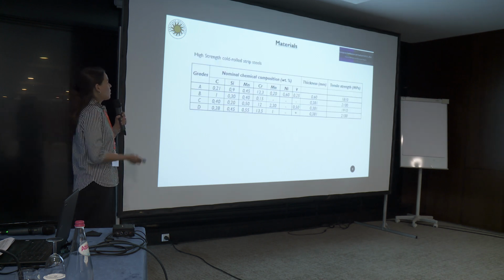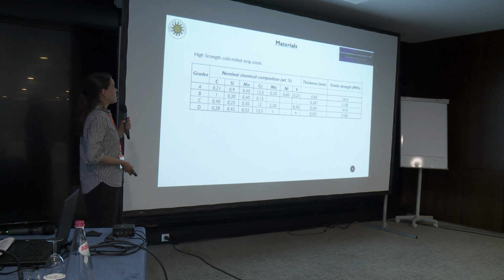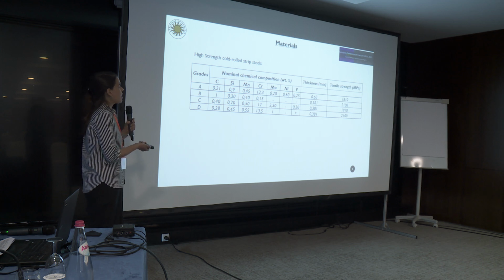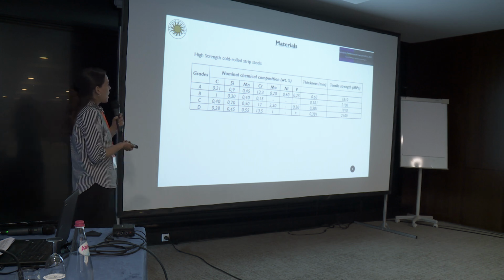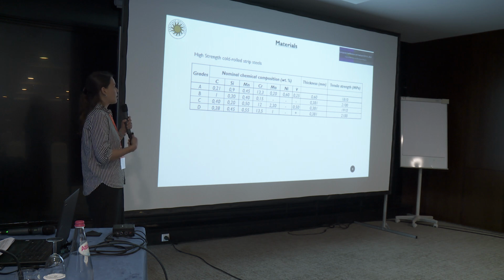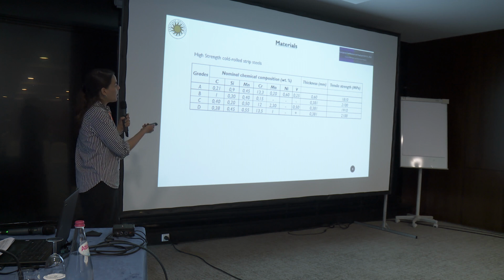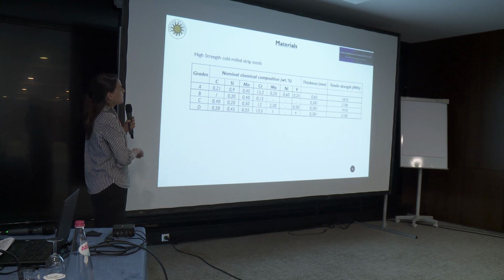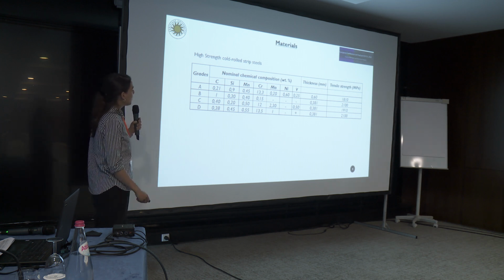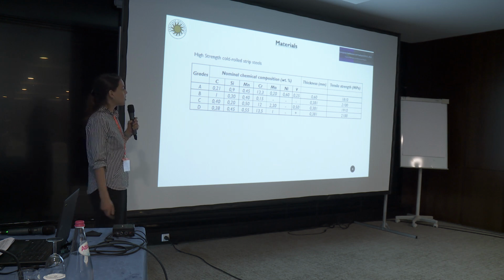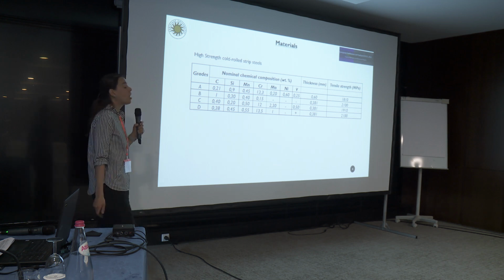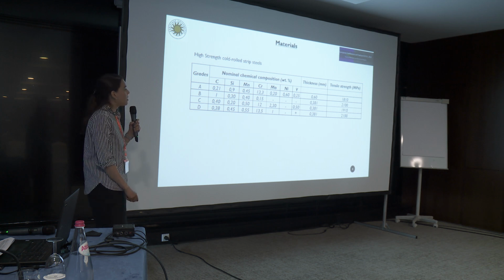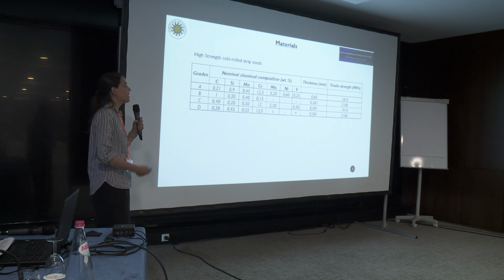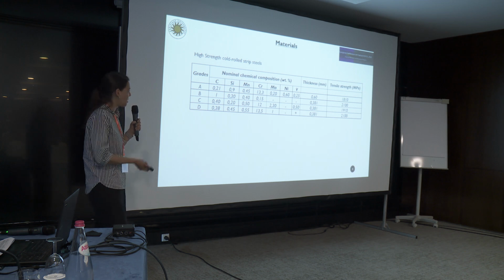In that table, you can see the 4 tested grades, A, B, C, and D, the chemical compositions, the thicknesses, and the tensile strength. Grade B is a high carbon steel. Grades C and D are stainless steels, and grade A is in between. We have 2 different thicknesses: grade A is 0.6 millimeters, and B, C, and D are 0.381 millimeters. They have a relatively high tensile strength, approximately 2,000 megapascal.